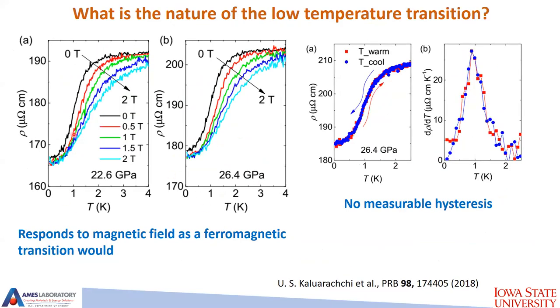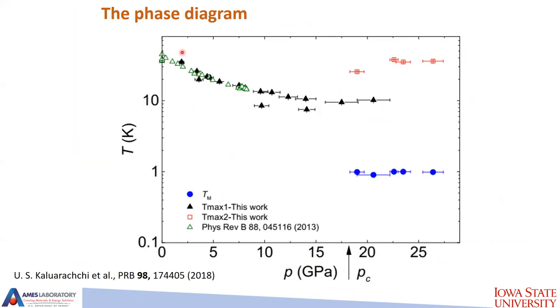Now, we applied field. This transition becomes broader and moves a little bit to higher temperature, so it responds to magnetic field just as a ferromagnetic transition would. There was no measurable temperature hysteresis. So all three features would look more or less like this on the phase diagram: the decreasing maximum, which is a proxy to the Kondo temperature, then a very different broad maximum at higher pressures, and more or less in the same pressure range, what we decided to call a magnetic transition.